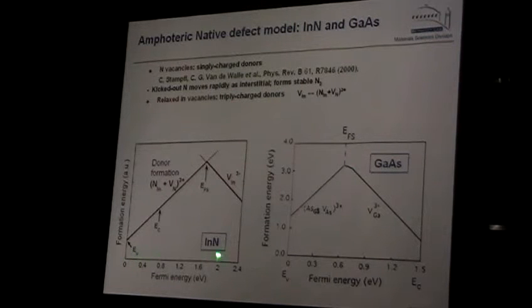This is towards the conduction band. So the conduction band edge of indium nitride is here. It's 0.7 electron volt from here to there. So you see that the formation energy of this donor-like defect is very low here. And this is what they are mostly for, until they reach this level of stabilization energy, and at this point it will be stable and the Fermi energy would not move at all.